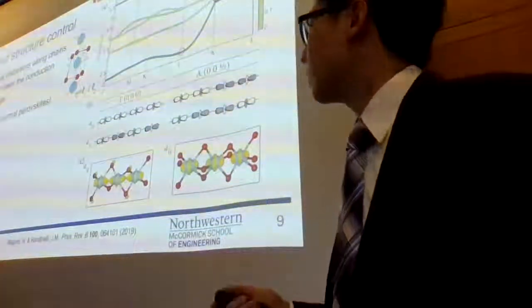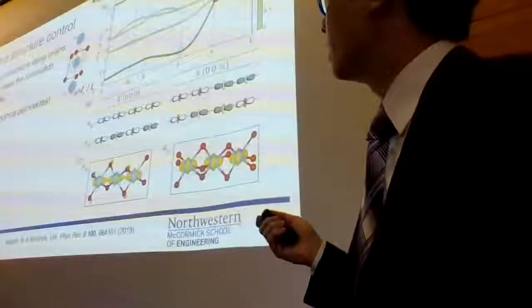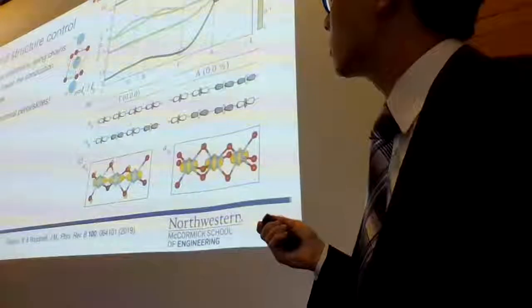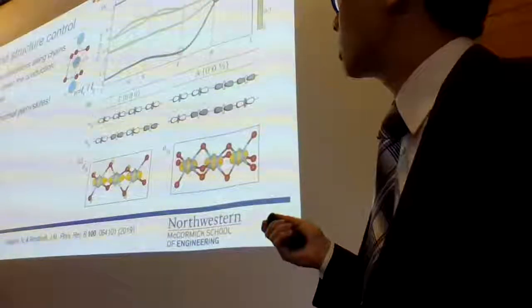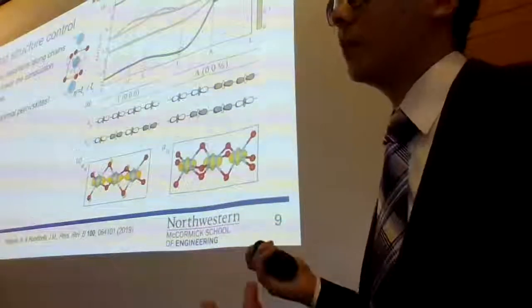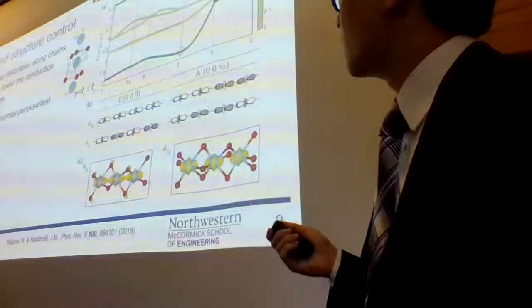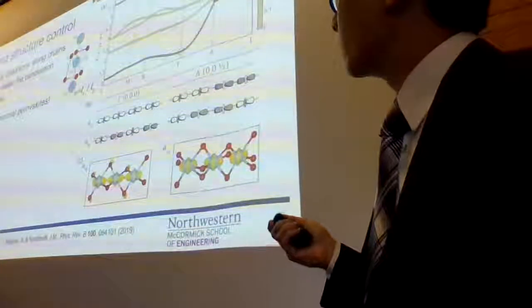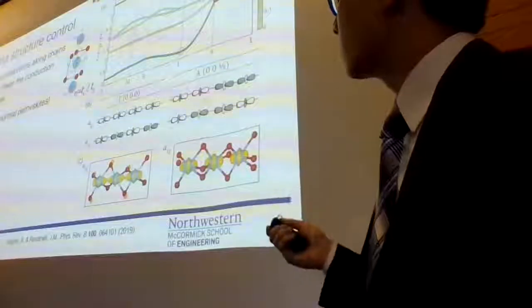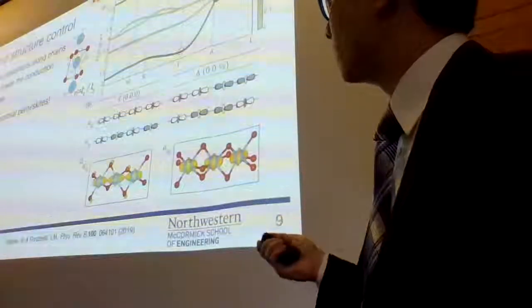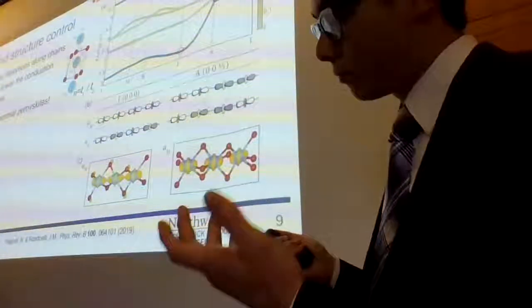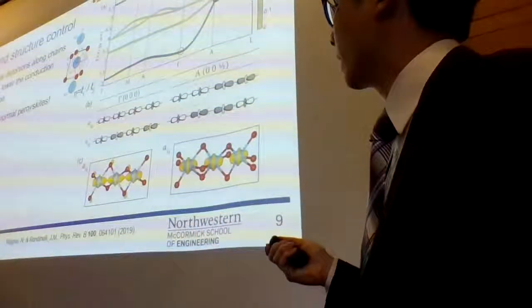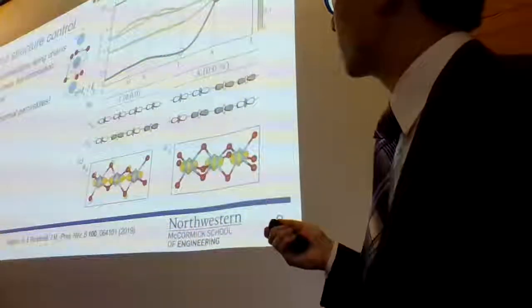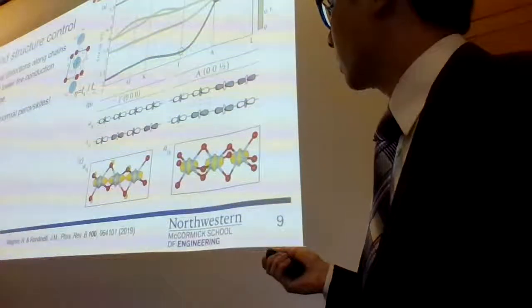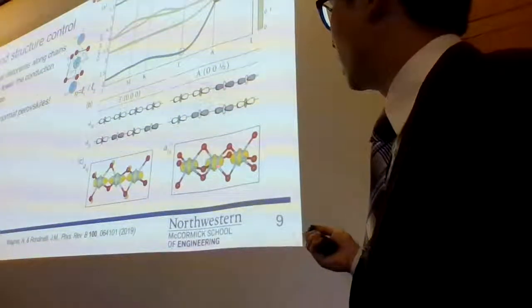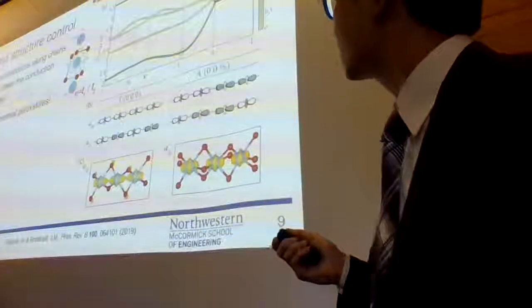But that's not the only interesting thing. One of the things I mentioned earlier is this eta parameter. So this trigonal distortion, which is defined as changing the ratio of these lengths to be not equal to 1. In the normal octahedral, they're 1. You could think about the effect of this on, say, the band structure. So this distortion, in the real material, gives rise to these bonding and anti-bonding A1G orbitals, which are oriented along the chains here. You can visualize the partial charge densities on the bottom here for the bonding and anti-bonding ones.